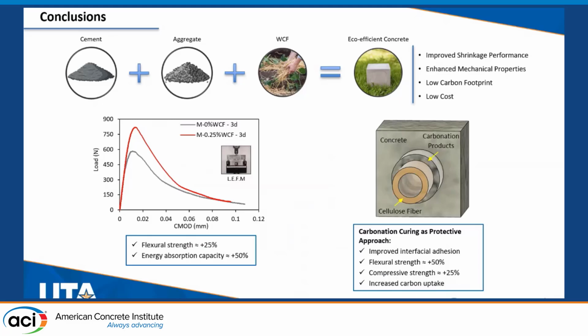In terms of mechanical properties, using WCF, we could enhance the flexural strength and energy absorption capacity up to 25% and 50% respectively, especially at the early ages. And to preserve the long-term mechanical properties, we had to protect the fibers, and we applied carbonation curing as our protective method, which resulted in improved interfacial adhesion and enhanced mechanical properties. Of course, there are a lot of other properties to check. That's why we are here in the research in progress. And these days, we know that these fibers can enhance the carbon uptake, and that's what I am investigating in my research.